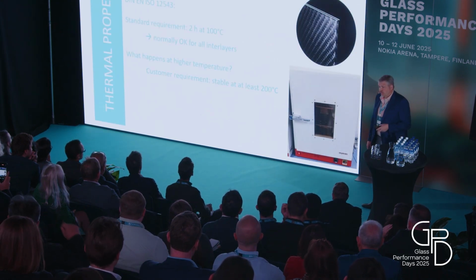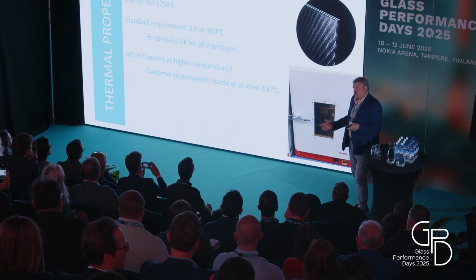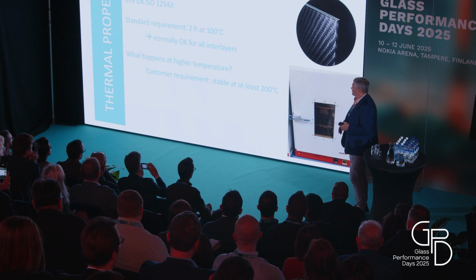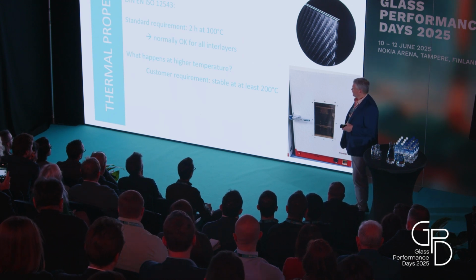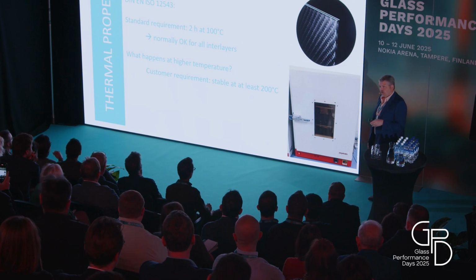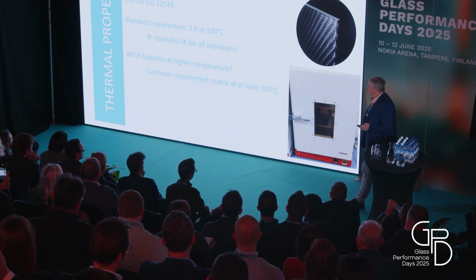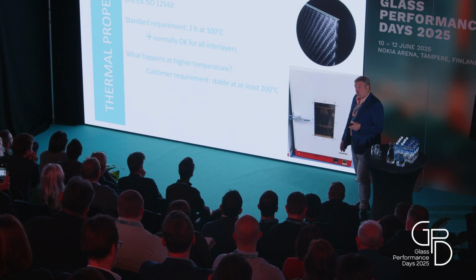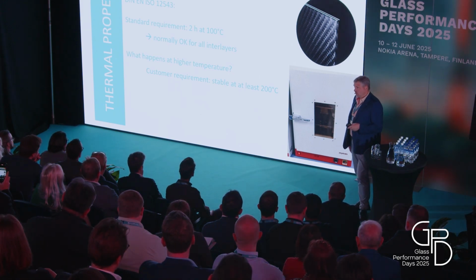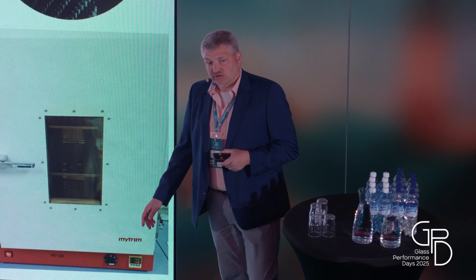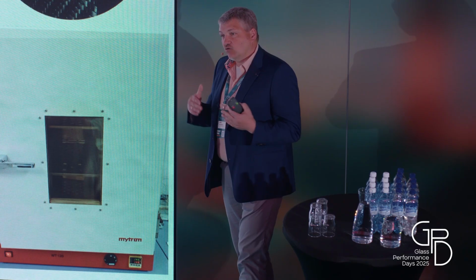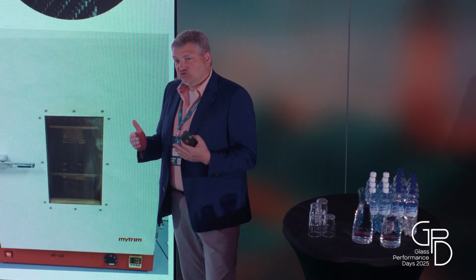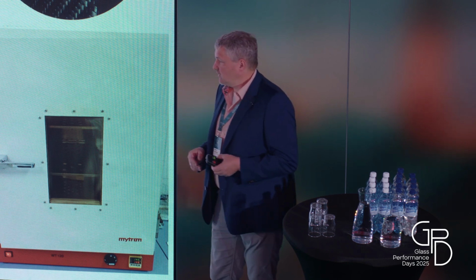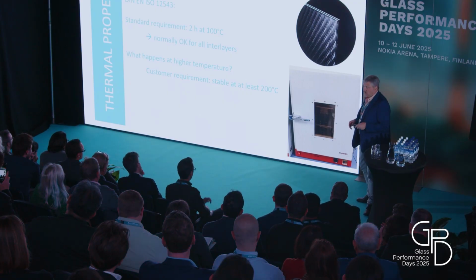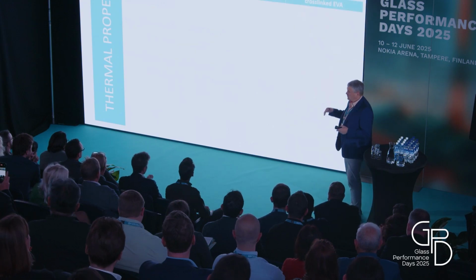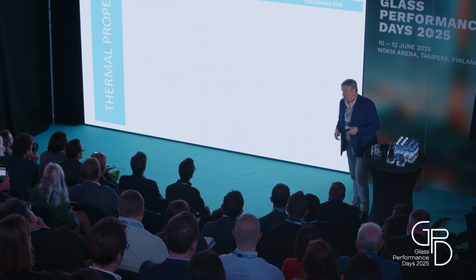Okay, now I'm bringing a few case studies with me because I want to show what's the difference between thermoplastic interlayer and the cross-linkable material. At first, we have chosen a bake test. It was already this morning in this discussion here. Typically, you run this test for 2 hours at 100 degrees C. Okay, normal behavior, no interlayer will get a problem. But then you have customers asking, okay, what if I need an interlayer or laminated safety glass with a temperature stability up to 200 degrees C? So the question comes, and we have done then a test in cooperation with an institute, making laminates, putting them into an oven, increasing temperature, and let's see what happens.